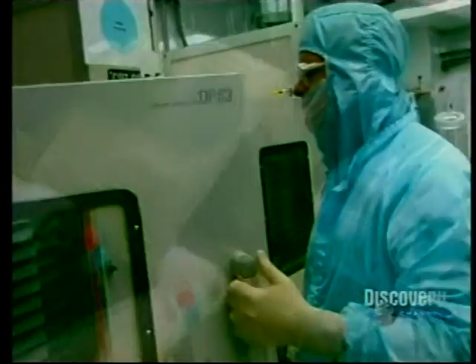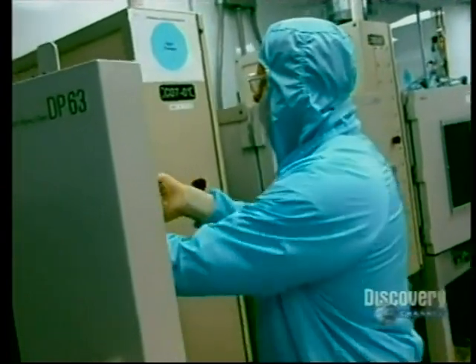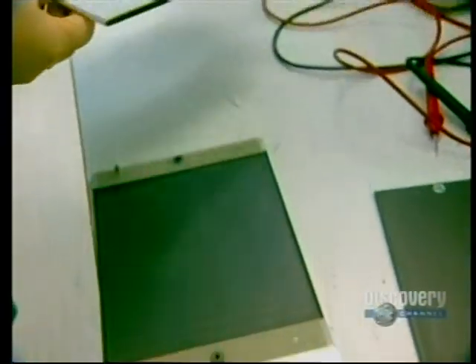To make an individual battery cell, the sheet has to be rolled up. This automated spooling machine winds up the lithium film in 26 revolutions. The wound-up sheet is put into a vacuum oven, where the various layers adhere firmly to one another. This step lasts for about 90 minutes at 176 degrees.